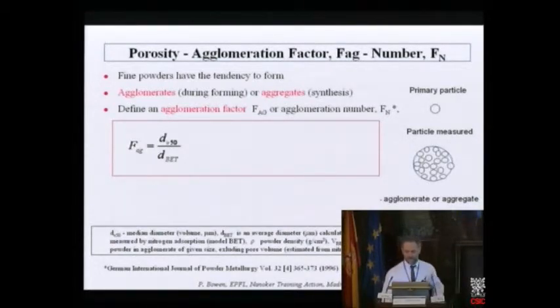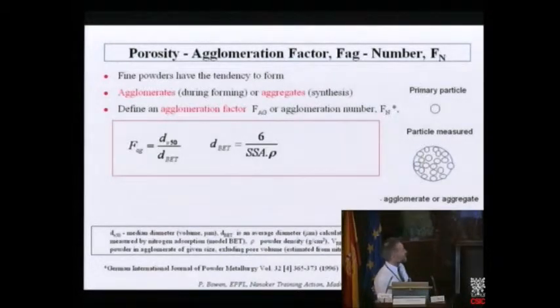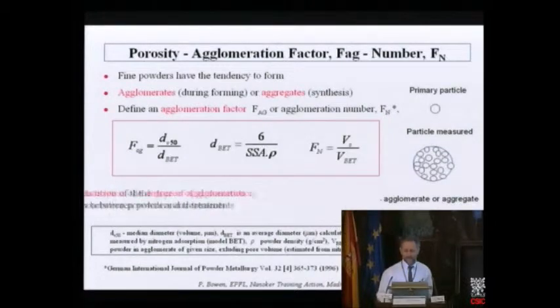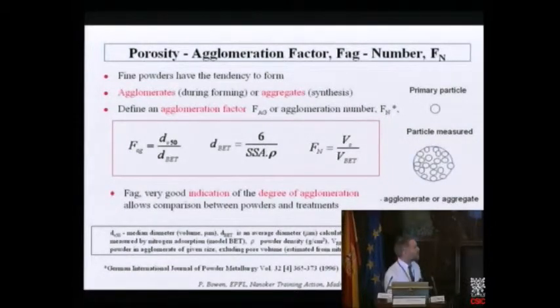the BET, which is from the specific surface area, so we can calculate an equivalent primary particle diameter using this formula, where this is the specific surface area, this is the density. This assumes that we have monodispersed primary particles that are spherical. This gives you a very good indication of the degree of agglomeration. We can also calculate the agglomeration number.